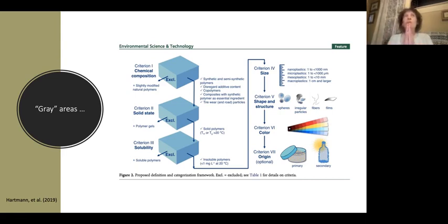We're able to analyze plastics that are 1 micron and larger using standard instrumentation like FTIR and Raman, as well as pyrolysis GCMS, which I'll talk a little bit about later in the course, whereas particles that are smaller than 1 micron are more difficult to analyze. They're difficult to pull out of the environment and identify. And so most of the work done on nanoparticles, for that reason, is done with particles that are purchased commercially and then used in laboratory exposures, rather than looking for them in biota or water samples or sediment samples.